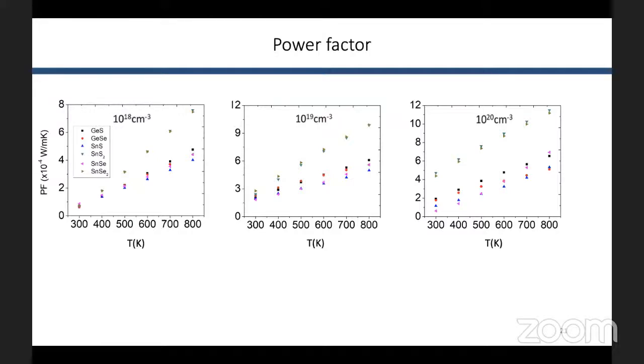And the same trend as electrical conductivity, power factor increases as a function of temperature, where tin disulfide and tin diselenide have higher values of power factor. And this could have some impact in the ZT equation. If you remember, ZT is power factor over the thermal conductivity. And if we expect higher values of power factor, we will obtain better values of ZT.